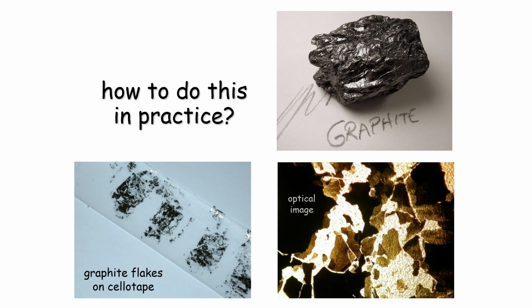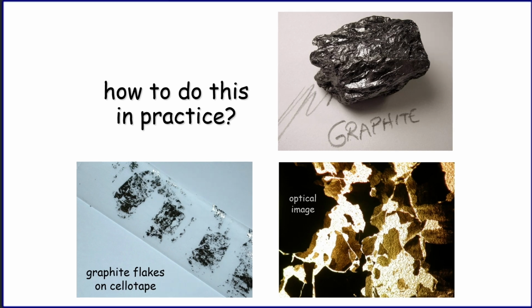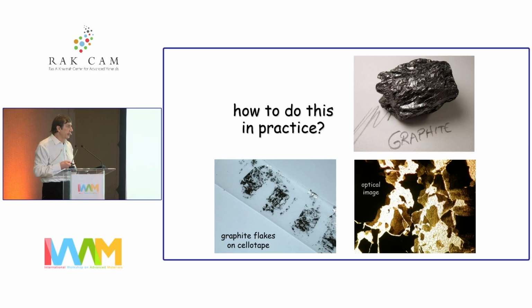And it was kind of a eureka moment for me, because graphite is a metal, and a pretty good metal, relatively speaking. So if a metal is transparent, it means it's a very thin metal. And I know from my experience that some of those most transparent flakes are 1 nanometer thickness, 5, 6 layers, something like that. When I saw this image 20 years ago, I knew that such 1 nanometer thin films are essentially impossible to produce by any means which we normally use, evaporation, deposition, and so on.